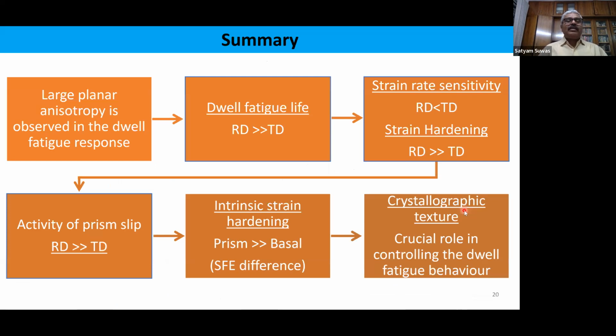So with this understanding, we could summarize this part. Particularly, a larger planar anisotropy is observed in dwell fatigue response, and definitely it is anisotropic, and dwell fatigue life is higher along RD than TD, and strain rate sensitivity is lesser in the case of RD than TD. Strain hardening response is higher in the case of RD than TD, and activity of prism slip is the one which is more in RD than TD, and that is responsible for intrinsic strain hardening of the material, and that is also accounted for the difference in stacking fault energy.